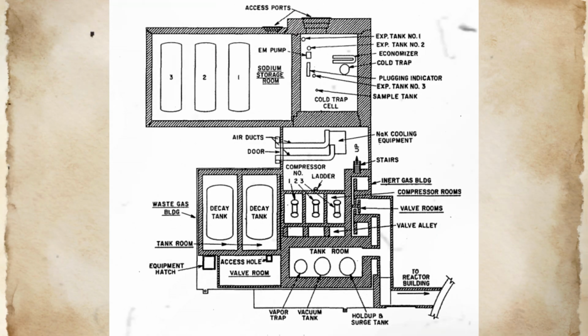The failure chain analysis revealed how multiple physical processes interacted to create consequences that exceeded the effectiveness of individual protection systems designed to prevent fuel damage. The reactor's thermal design margins, control system responses, and emergency detection systems were all appropriate for the individual challenges they were designed to address, but their combined effectiveness was insufficient to prevent core damage when the fundamental assumption of adequate coolant flow was violated by an unanticipated debris blockage mechanism.